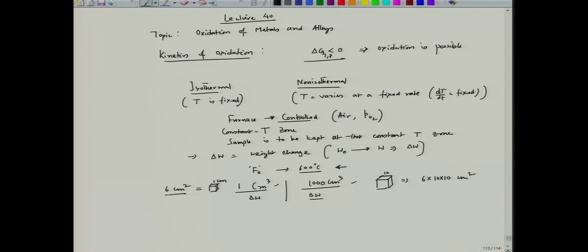So, the surface area exposed to the oxygen in this case would be much higher. So, del W would be much higher in this case. In order to avoid this area factor, we have to divide it by the initial area, which will normalize it with respect to the difference in area. So, this is A1, this is A2, and then we should get the same level of this parameter for a particular time interval.